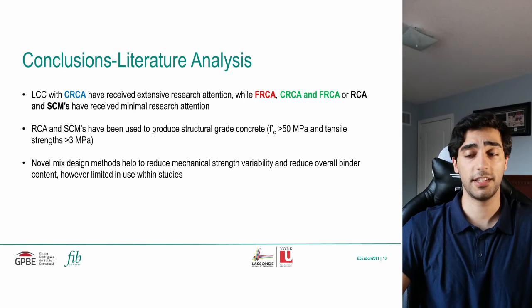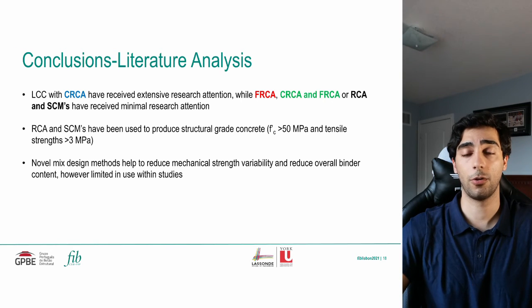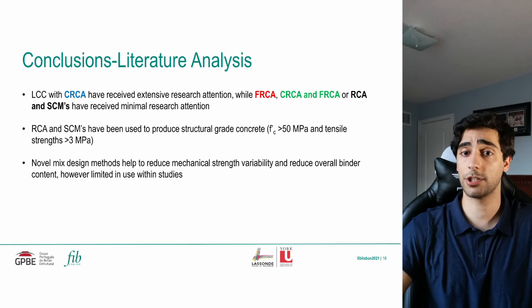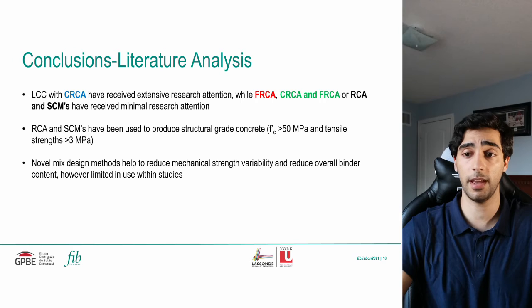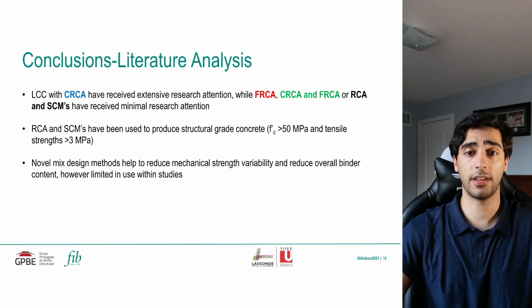Now, to conclude everything, going back to the literature analysis, low-carbon concrete with CRCA have been extensively studied in research, while the use of fine RCA, coarse and fine RCA, or RCA with SCMs have received minimal research attention. However, despite the reductions observed within many research studies, the use of recycled concrete aggregates and SCMs have been able to produce concrete with compressive strengths over 50 MPa and tensile strengths over 3 MPa. As well, literature analysis also found that novel mix design methods can help reduce mechanical strength variability and reduce the overall binder content of the mixtures.